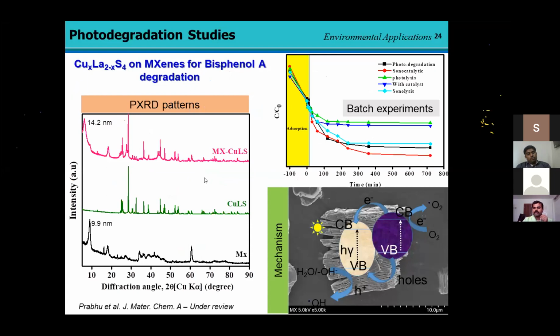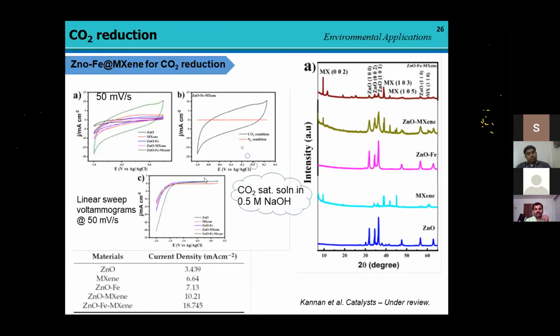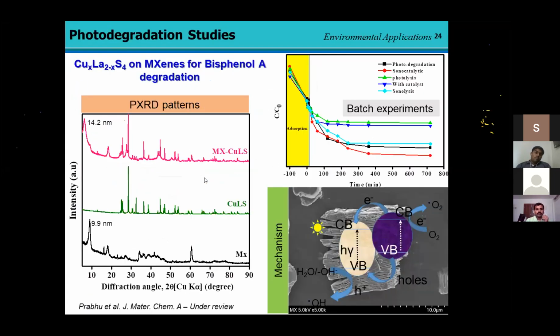Then another similar work was done here at Alagappa University. We have started with copper lanthanum sulfide and MXene for bisphenol A degradation. We found that these particular bimetal sulfides are intercalated, confirmed by PXRD studies, when the d-spacing value increased drastically from 9.9 to 14.2. This MXene material was totally delaminated.